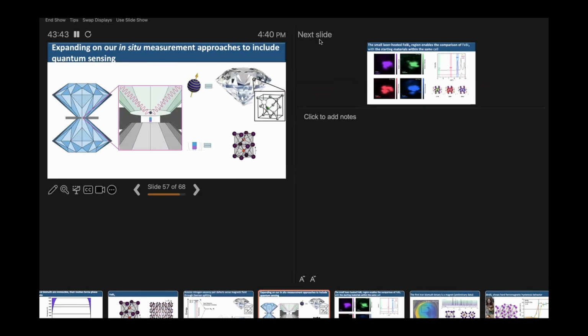Now, the really cool thing about using a diamond is diamonds are transparent to everything. So what we can do with the diamond anvil cell, 100 microns sounds really small, but we can rasterize like 100 spots and get the diffraction pattern at every one of those spots. And then we can directly correlate our diffraction patterns to our measurements of our magnetic moment. The other thing is, nitrogen vacancy centers naturally have 4 different orientations in the diamond. And so we can use the 4 different orientations relative to an external magnetic field to start to get information about the magnetization of our material.